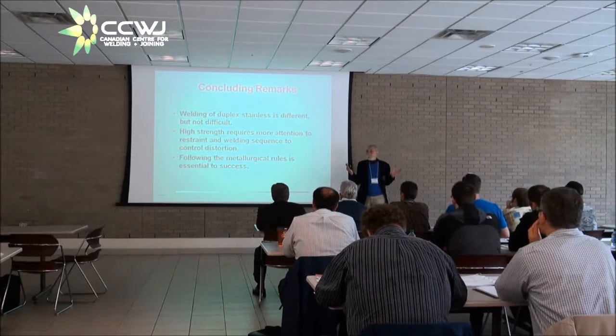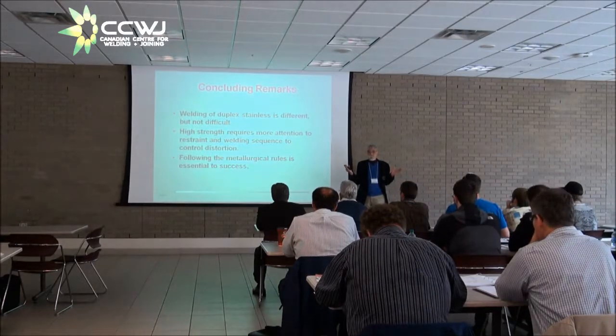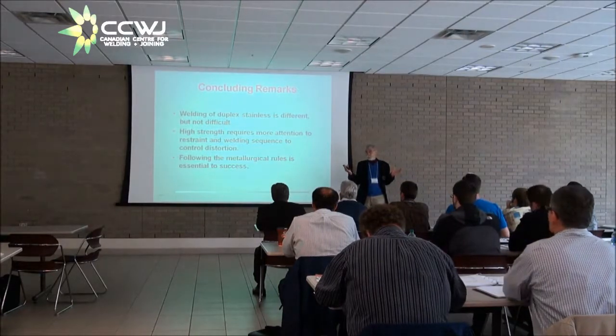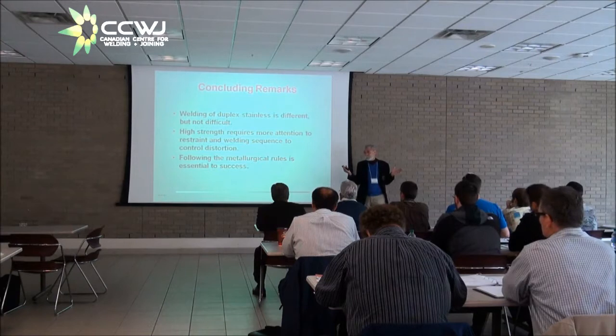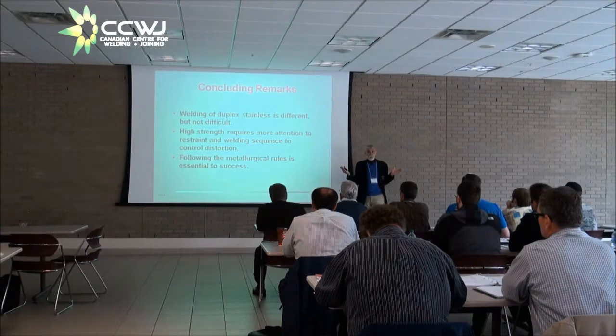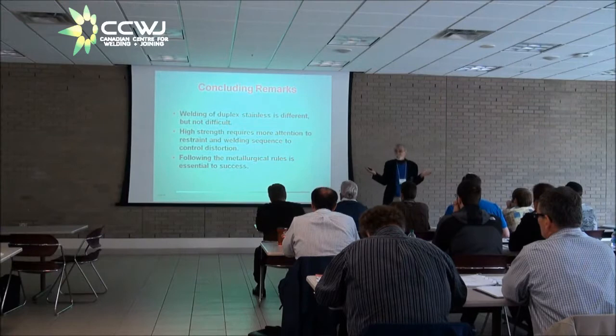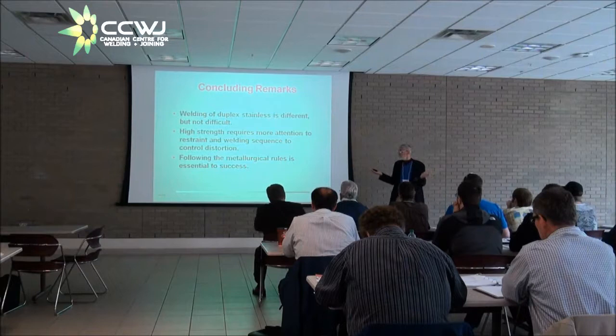If you're going to restrain duplex when you weld it, you don't want to use bungee cords to hold it down. You want to use massive restraint to keep it from distorting. Because it develops strength more rapidly and it is stronger than austenitics, it will pull more if you do a light restraint job. You've got to do heavy restraint.